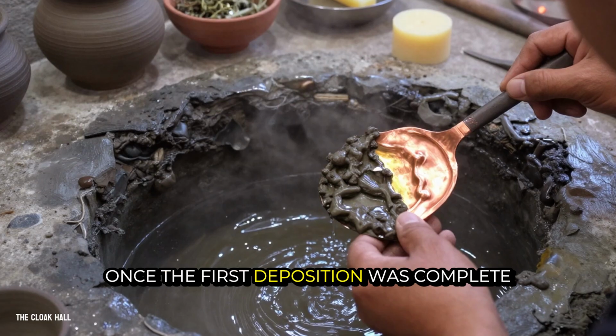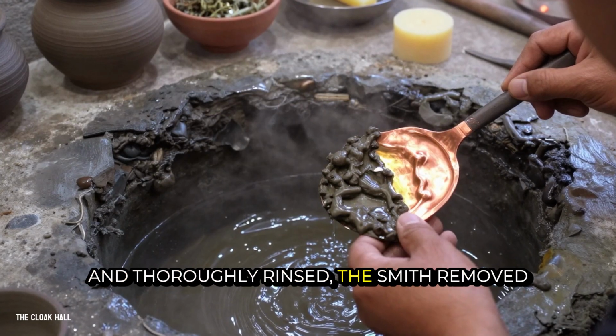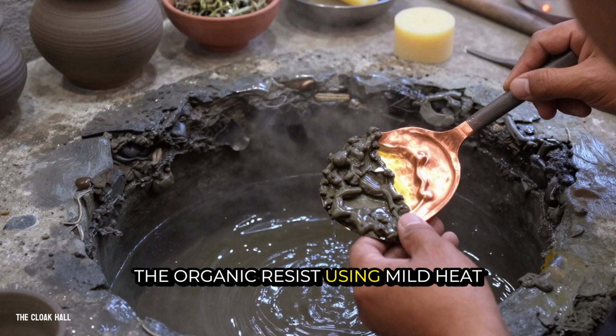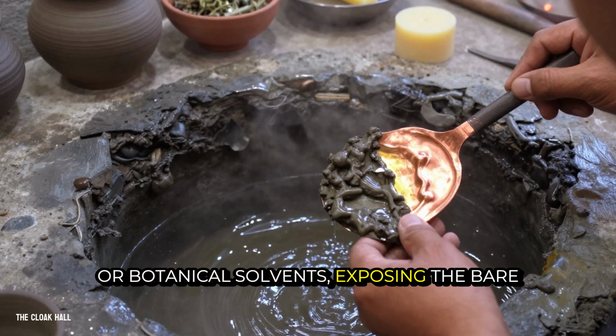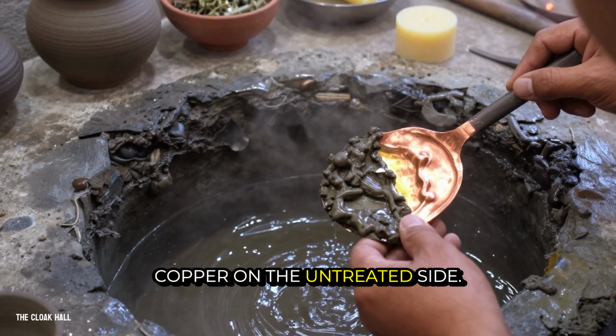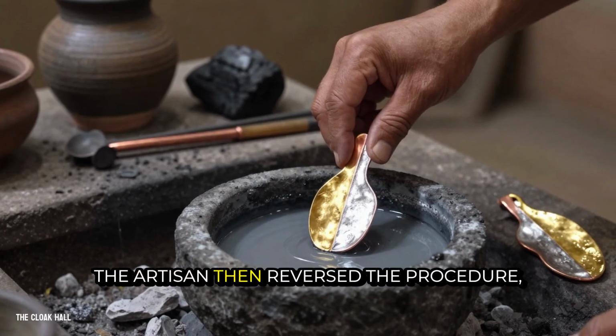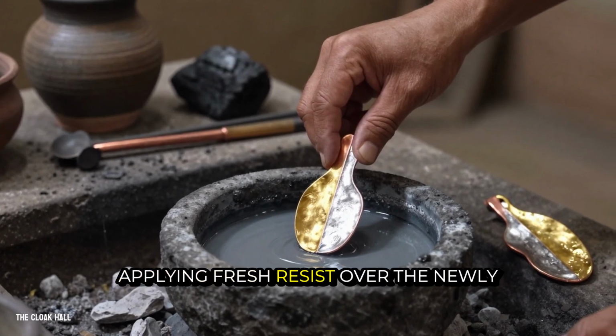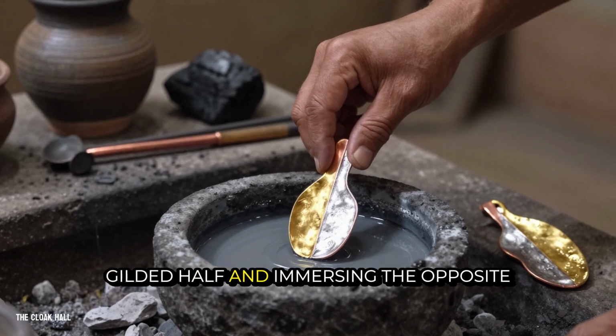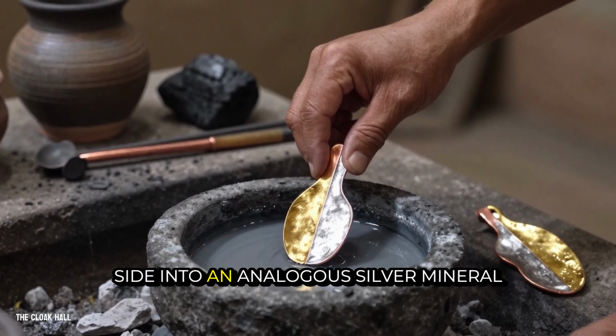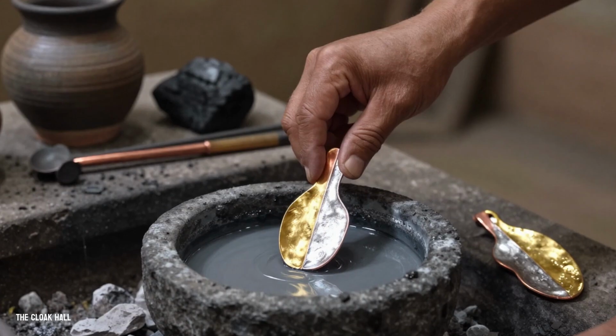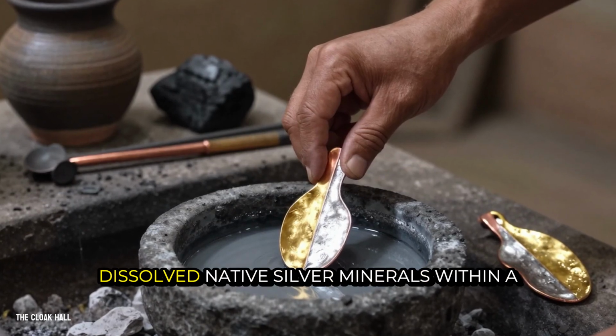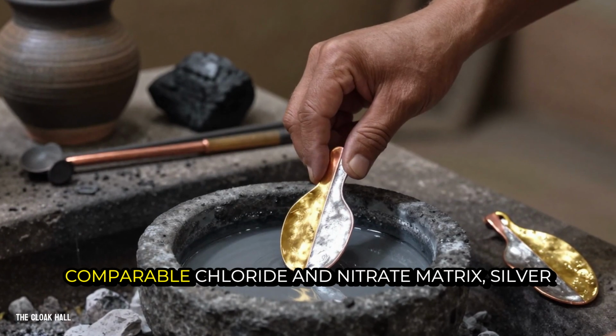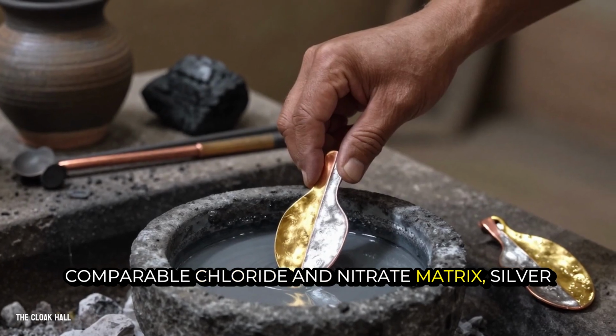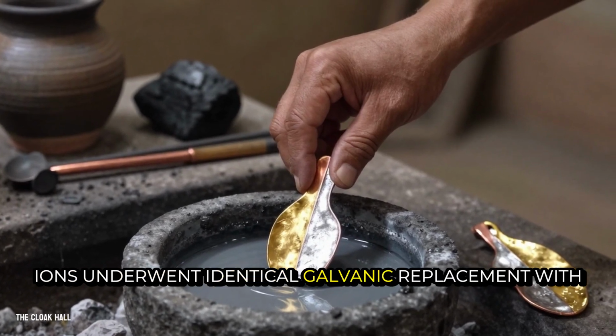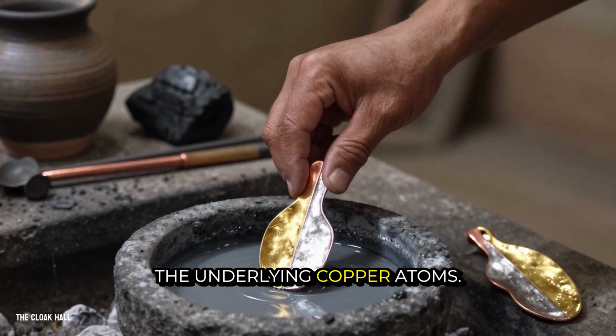Once the first deposition was complete and thoroughly rinsed, the smith removed the organic resist using mild heat or botanical solvents, exposing the bare copper on the untreated side. The artisan then reversed the procedure, applying fresh resist over the newly gilded half and immersing the opposite side into an analogous silver mineral bath. In this silver electrolyte, composed of dissolved native silver minerals within a comparable chloride and nitrate matrix, silver ions underwent identical galvanic replacement with the underlying copper atoms.